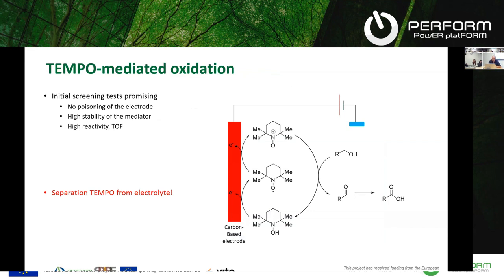So tempo-mediated oxidation, how does that work? You have the radical, the tempo radical, which is actually oxidized to the positive ion, as you can see in this picture, and this reacts with the primary alcohol on, for example, a glucose molecule. Then the tempo is again reduced to the OH form and can be recycled at the electrode surface. Initially, these tests that we did on a very small scale, what Erwin also showed in his presentation, the first step with H cells, we saw no poisoning of the electrode. We also see that there's a high stability of the mediator, so it doesn't get broken down at the anode. And we have a very high reactivity and turnover frequency.